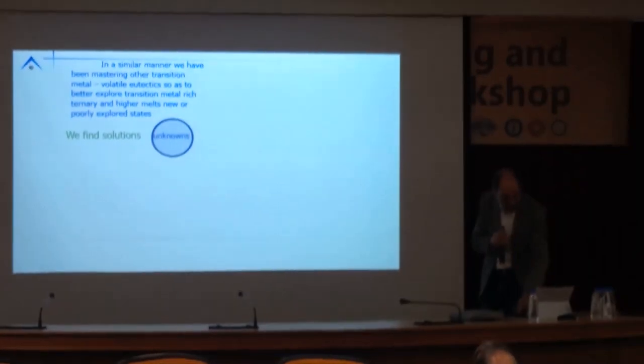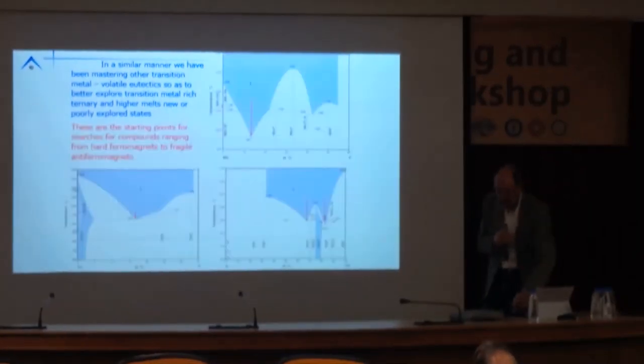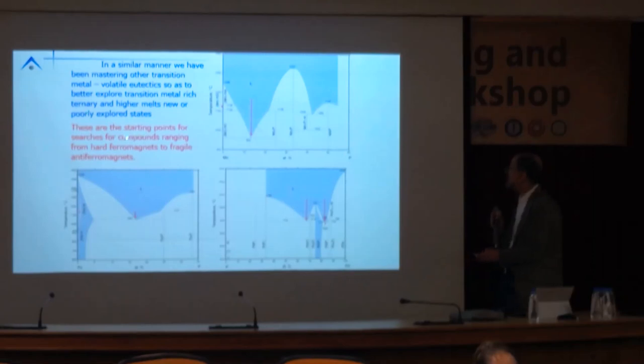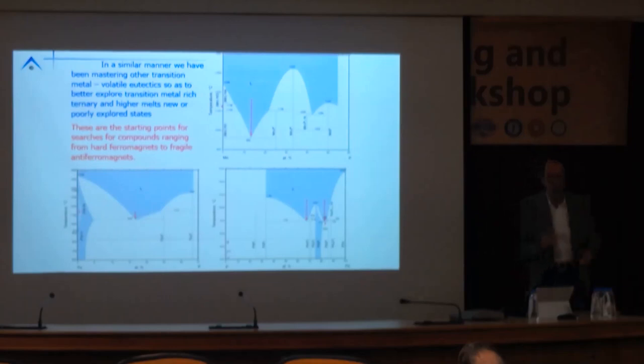Now, we can extend that. We can go away from nitrogen and look at other systems. In one of my other jobs, we're trying to find new ferromagnets, okay? If we want to do that without rare earths, we can look at transition metal-rich systems, manganese or iron, and we can put in phosphorus, okay? Phosphorus is relatively volatile. It's hard to work with in an arc melter, but these eutectics, it turns out, have virtually no vapor pressure above them. So they're very promising liquids to go and discover new materials out of them.